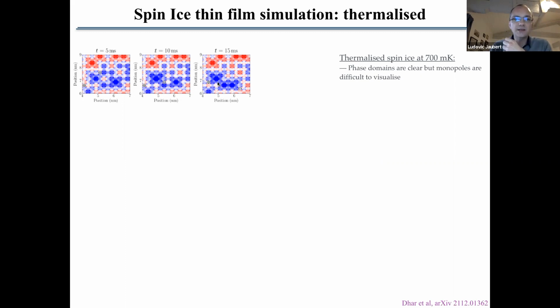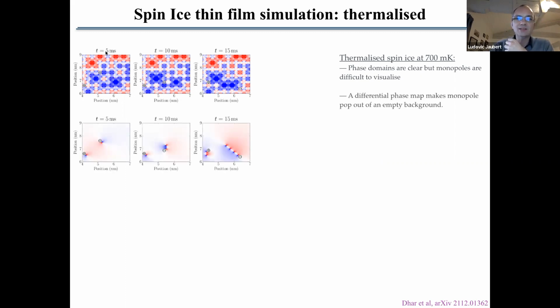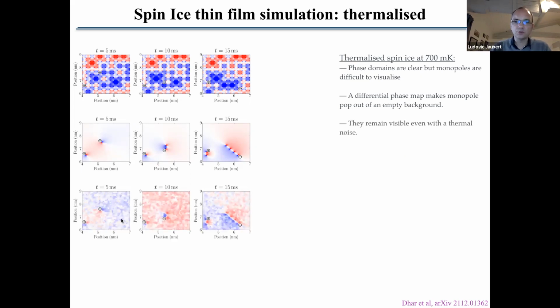But so what you can do is you can measure the phase map at time t equals 0, and then at different times, and you can subtract the two. So you can do a differential phase map here. And then if you do that, this differential phase map enhances all the changes you have between time t equals 0 and times t at 5 milliseconds, 10 milliseconds, 15 milliseconds. And so in this case, you can really see the movement of the monopoles. So here you see that the tip of the monopoles, the presence of the monopoles, are very clear in this phase map. And even if you add numerical noise to try to represent experiments, you can still clearly see the discontinuity and the singularities there.